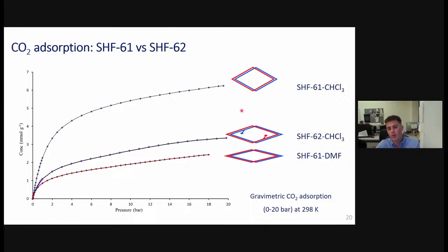And the final thing that we wanted to look at was how does this post-synthetic modification affect the adsorption properties? So we can overlay the analogous gravimetric CO2 adsorption data. So these were all taken at 298 Kelvin. And we see we're somewhere in the middle of where we were in terms of Sheff61 chloroform and DMF. So it's not quite as high as this open pore framework, but it has a higher capacity than when we activate the original framework from DMF.